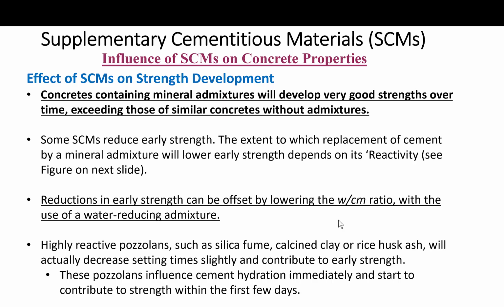Reductions in early strength can be offset by lowering the water-cement to cementitious materials ratio, along with the use of water reducing admixtures.